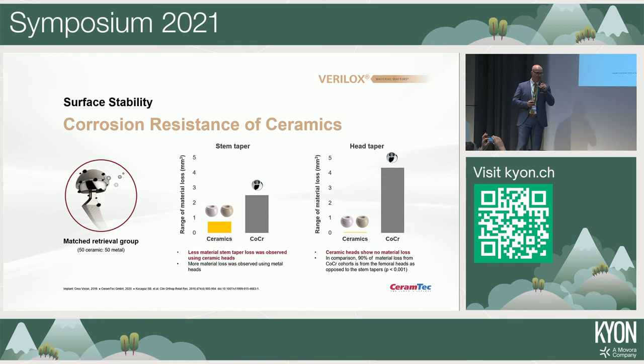And you see, on the stem side with ceramic heads, you get a lower amount of material lost from the stem. And of course, the head itself, the ceramic head itself, which is shown on the left side, doesn't lose nearly any material, while even the cobalt chromium head loses material on the side in a significant amount.